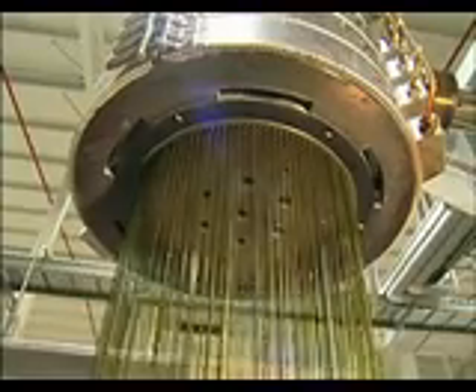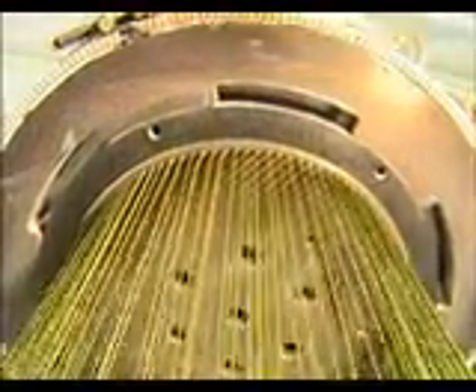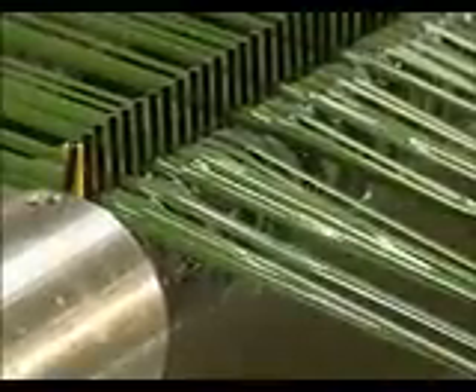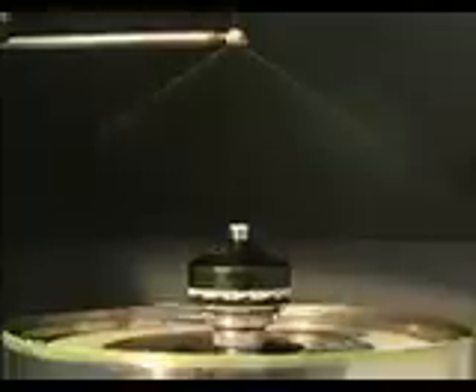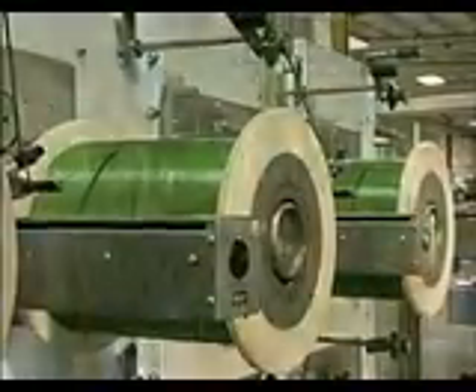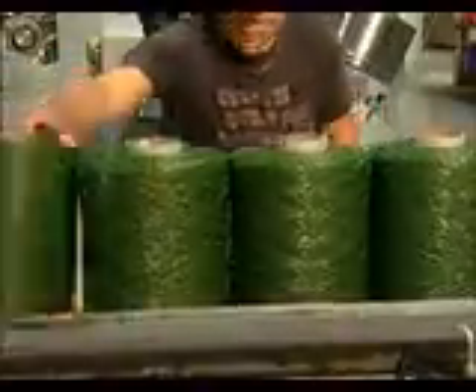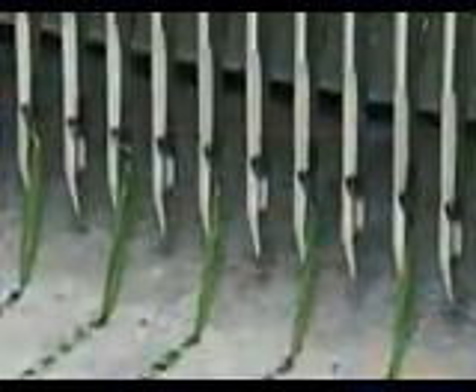An alternative to fibrillated fibers is the monofilament fiber, designed specifically for high-performance sports turf applications. To make a monofilament fiber, the compounded polyethylene resin is extruded directly from a spinneret as individual polyethylene fiber strands. The profile of the fiber is controlled with one of several die patterns we use. A liquid bath controls the cooling of the monofilament fiber so it stays consistent in density and thickness. As with our fibrillated fiber, this consistency is key in determining the turf's durability and resilience. These natural grass-looking monofilament fibers are then twisted into bundles of 6 or 8-ply blade configurations. This forms the yarn, which is then wound onto cones and shipped to turf manufacturers, who then tuft the yarn into finished turf, much like carpeting is made.